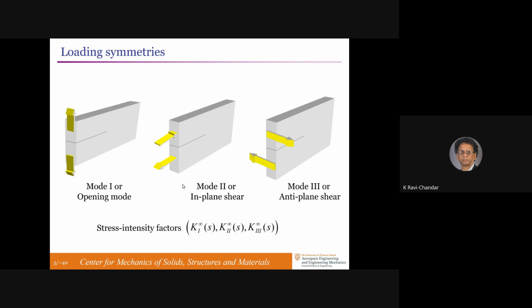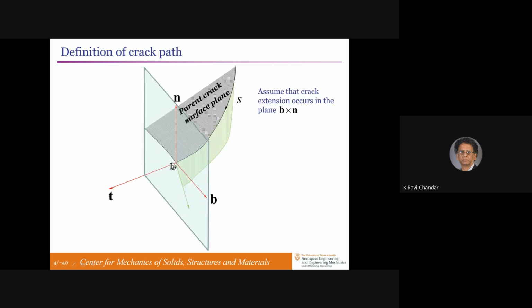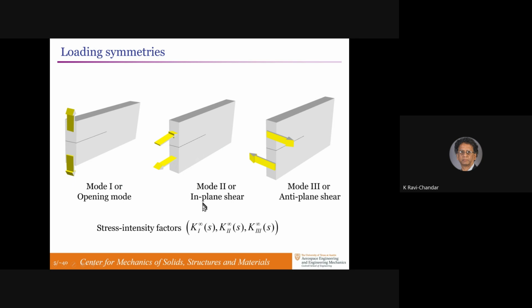Now, in the NB plane, you can have three classical fracture symmetries: mode 1 opening mode, mode 2 in-plane shear, and mode 3 out-of-plane shear. And I'm assuming everybody has had a course in fracture mechanics, that these cracks are governed by the magnitude of the load described in terms of the local values of the stress intensity factors applied on these cracks. So at every point, we're going to subject it to a combination of K1, K2, K3 with a superscript infinity to indicate that these are under opening, in-plane shearing, and out-of-plane shearing loading. What is the criterion for growth of these cracks?